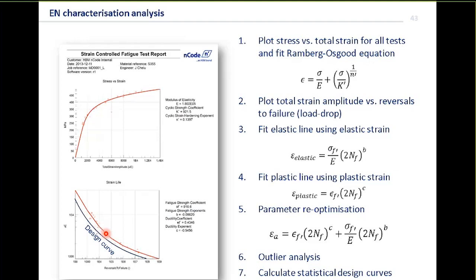In an outlier analysis, we're looking for points which don't lie on that curve. Now, some of that's going to be just statistical scatter, and we're going to use those in our design curve, so we're not worried about those. But some of them are clearly indicating that they don't lie on that regression line. And that's very interesting. We need to know, why is that? Can we exclude them? Have they failed in the grips or something like that, which makes it an invalid test? Or is it really a valid test?